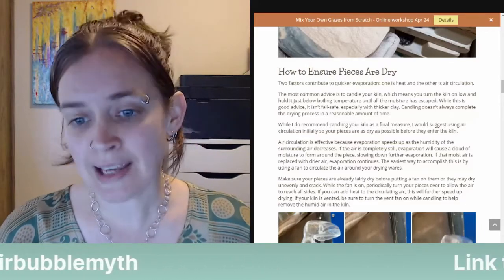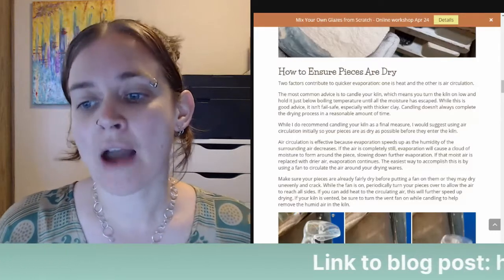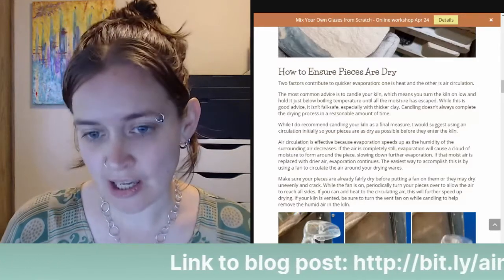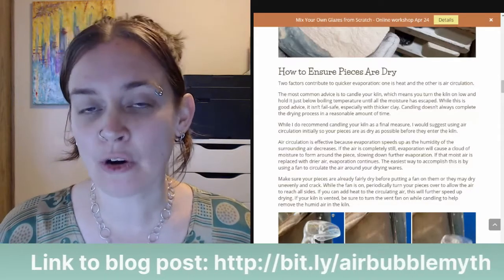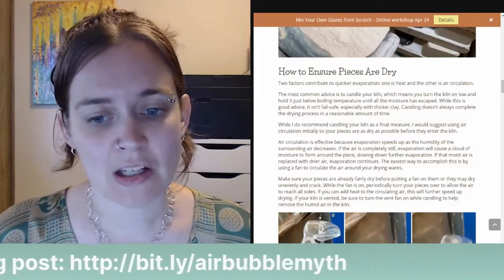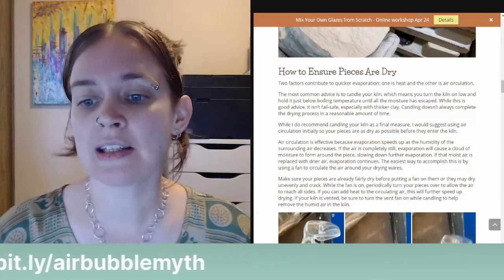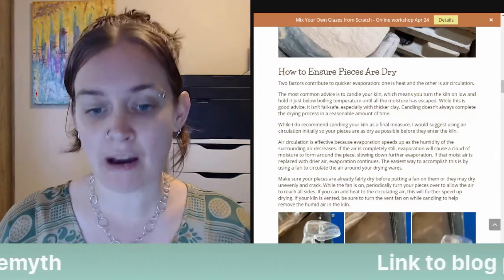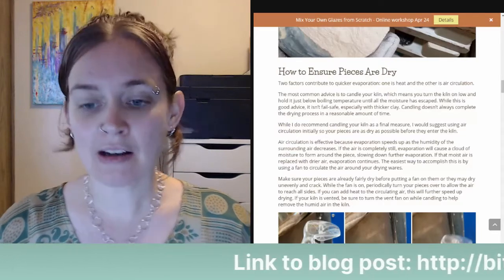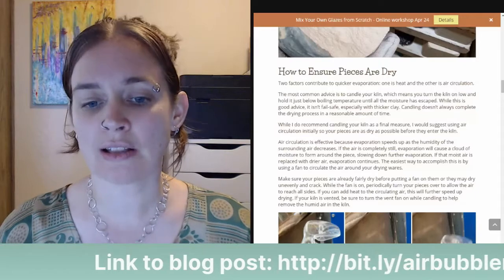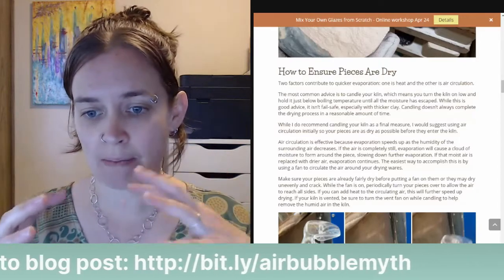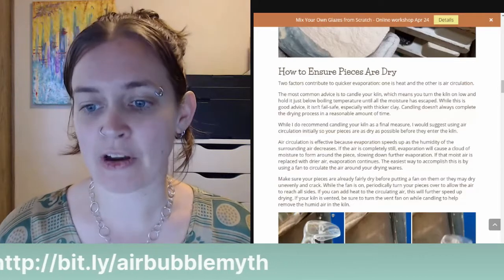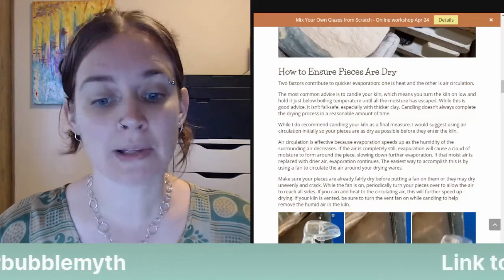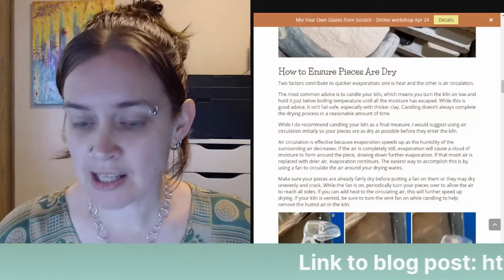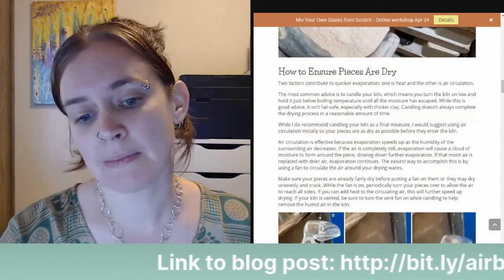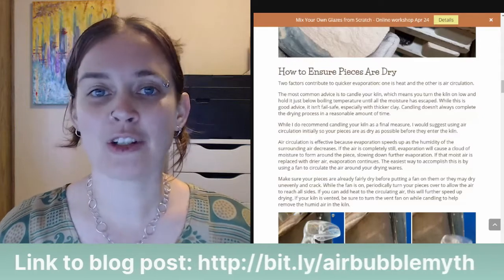While I do recommend candling your kiln as a final measure, I would suggest using air circulation initially so your pieces are as dry as possible before they enter the kiln. Air circulation is effective because evaporation speeds up as the humidity of the surrounding air decreases. If the air is completely still, evaporation will cause a cloud of moisture to form around the piece, slowing down further evaporation. If that moist air is replaced with drier air, evaporation continues. The easiest way to accomplish this is by using a fan to circulate air around your drying wares.